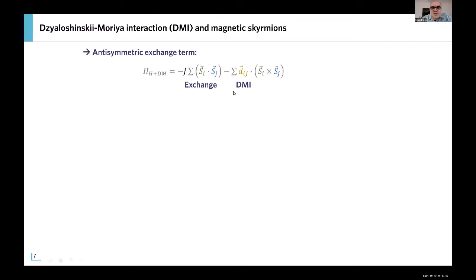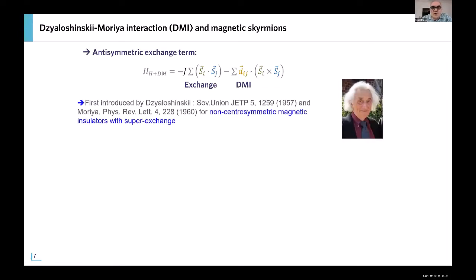Here you have the Hamiltonian that corresponds to the system, where you recognize, with this dot product, the exchange interaction, which favors a collinear configuration of neighboring spins, either parallel or anti-parallel. And you do have this Dzyaloshinskii-Moriya term with a cross product between neighboring spins. It means that this term favors a tilting of neighboring spins around this vector. And this, in fact, was first introduced 60 years ago by Dzyaloshinskii and then rapidly after by Professor Moriya, in order to explain the weak ferromagnetic component in a non-centrosymmetric magnetic insulator with superexchange.